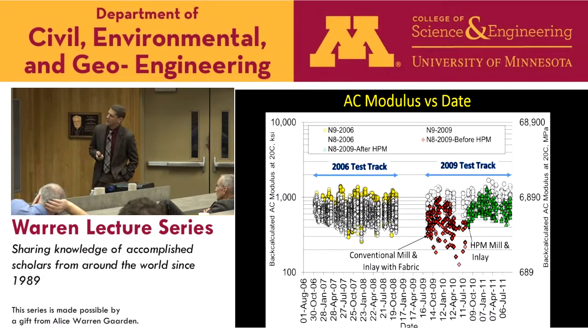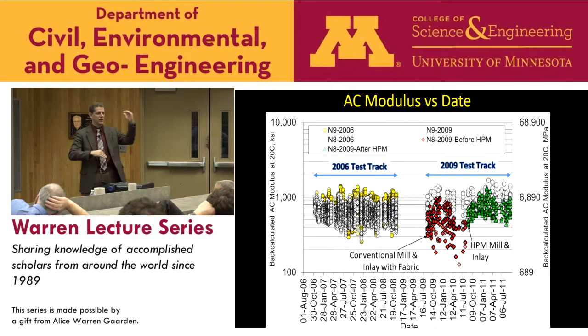This is showing a lot of FWD data where we've back calculated the layer properties. So this is AC modulus versus date, and this is the 06 track, the 09. The perpetual section, there's scatter in the data, just random variation, but you can see it increasing over time. The non-perpetual section, this is after we reopened to traffic and we had all that cracking going on and shearing. It's dropped quite a lot, and then when we did the mill and inlay, it immediately closed up the variability and improved. It did improve the structural integrity of that section, and you can see it pretty clearly in those modulus values.